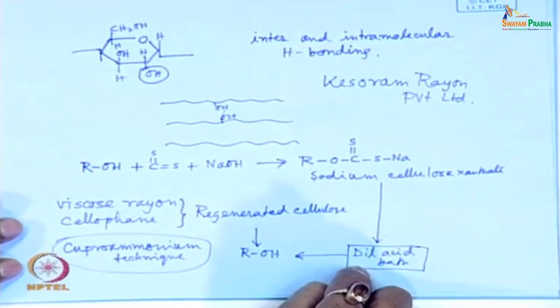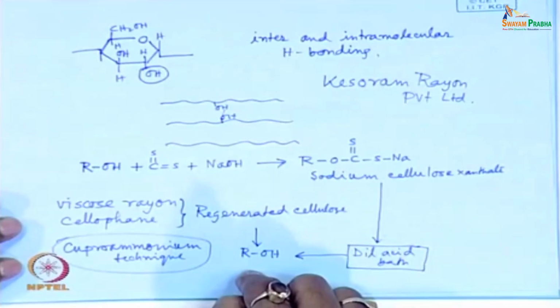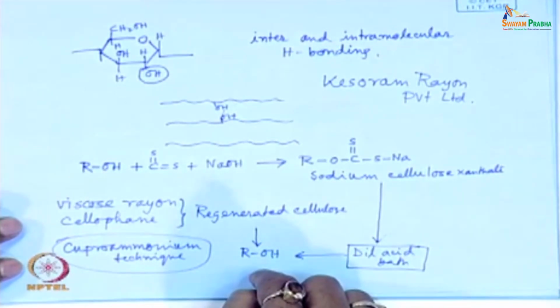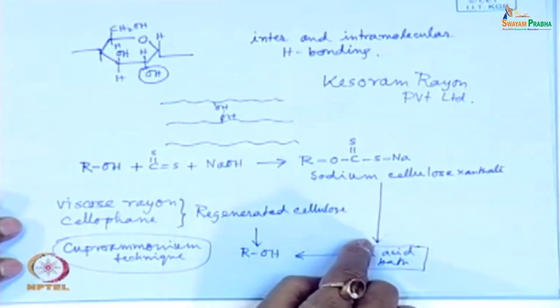You can verify it. You take the XRD of raw cotton, then you take the X-ray diffraction of this mercerized cotton. You will find that its crystallinity is reduced, that is due to decrease in hydrogen bond. Also, you can verify this with the help of Fourier transform infrared spectroscopy. There you will find that the extent, or concentration, of hydrogen bonding has decreased after this viscose treatment.